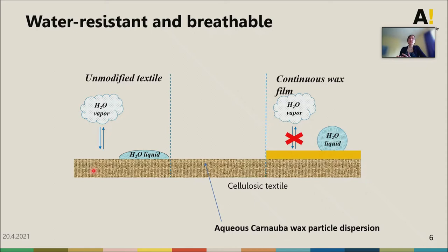Usually when we protect either wood or textiles, we use some kind of film-forming material. And this can introduce hydrophobicity, so it protects from liquid water. But unfortunately, this is not breathable. So it removes this nice breathability that the cellulosic material had. What we did instead was that we were inspired by nature, so we knew that if we increase the roughness, we will get a good hydrophobicity. And then we realized that we can have a very thin particulate coating, and this will be water resistant, but it will still let the water vapor go through.